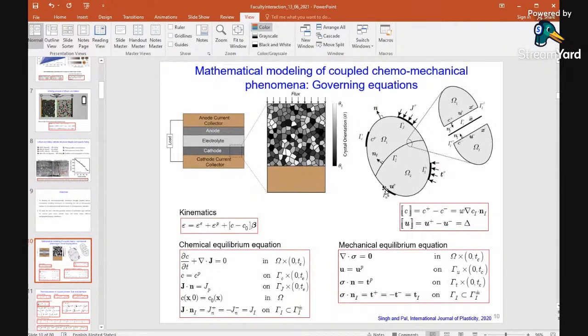Now I'll go to the mathematical model. On the left side we saw the schematic, and we have taken the current collector and the cathode together, with a polycrystalline microstructure where we have the crystal orientation. We define the kinematics, that is how the strain is generated within the structure: the elastic strain, plastic strain, and the strain due to the lithium diffusion. We have the chemical equilibrium equation and the mechanical equilibrium equation. We also consider that there is a two-grain junction. We utilize a separate continuum for the interface, where there is a concentration gradient and a displacement gradient. When the displacement between these two interfaces is critical, it will crack, and then there is no exchange of the lithium ion.